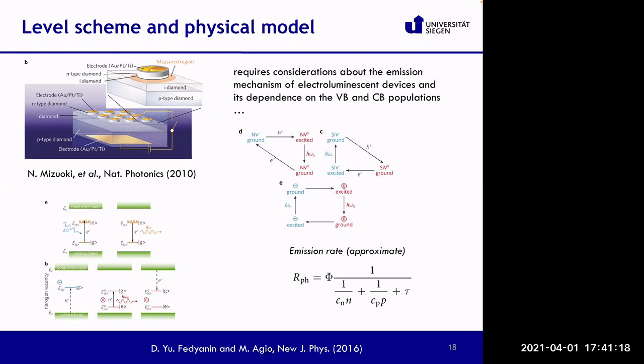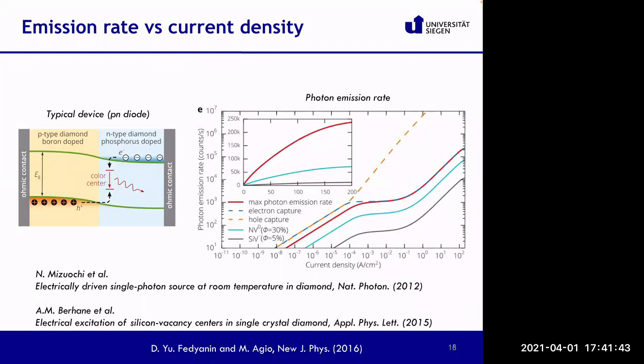And then you have these capture cross sections, which of course depend on the quantum emitter that you have, because they are also related to the levels of these emitters in the gap of diamond. So then there is a lot of technology to be done, and here you see some more theoretical results. So let's imagine that we are able to create a p-type and n-type diamond. So you have holes and electrons that travel, and at some point they meet a color center and they recombine to generate a photon. So based on this theory, you can estimate what will be the probability of emitting a photon, and therefore you can calculate the so-called emission rate, which is given in counts per second.